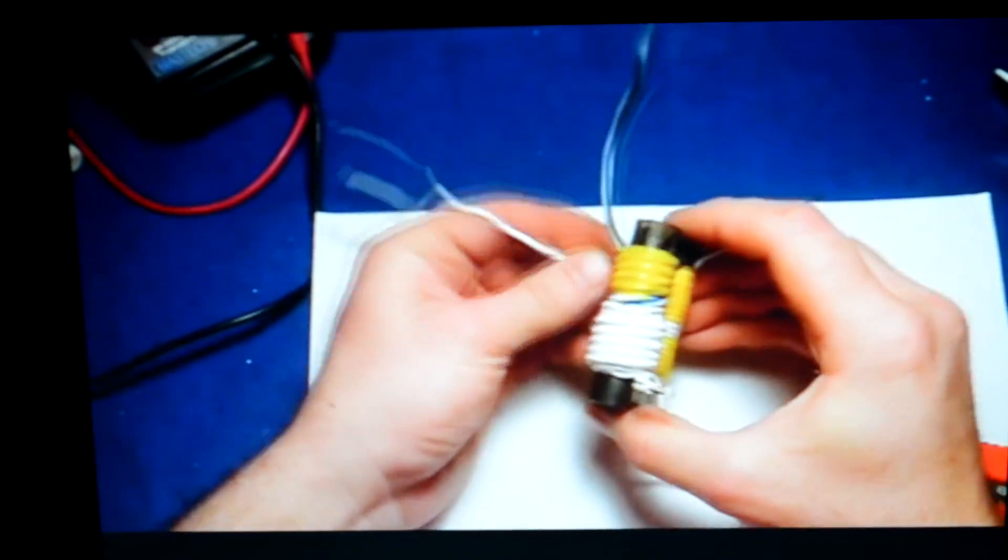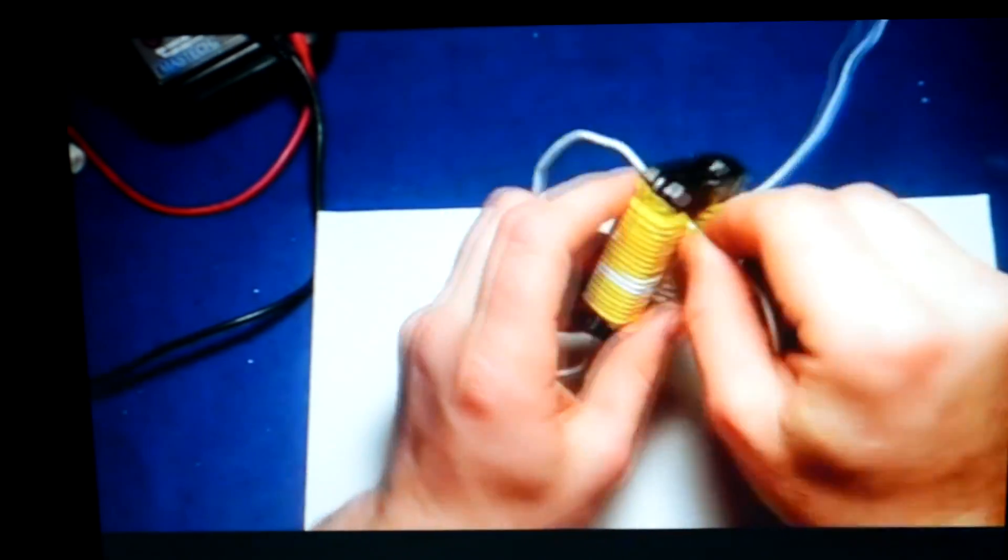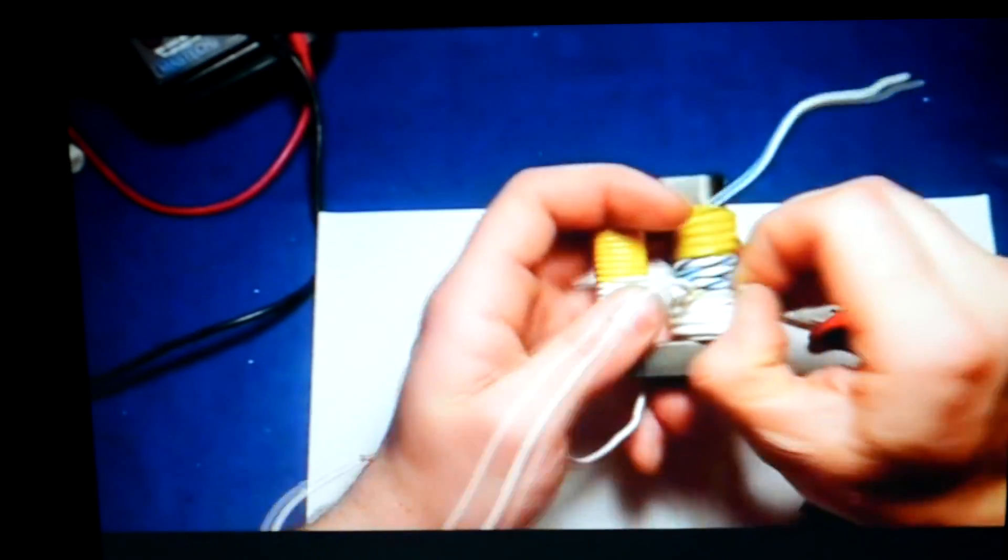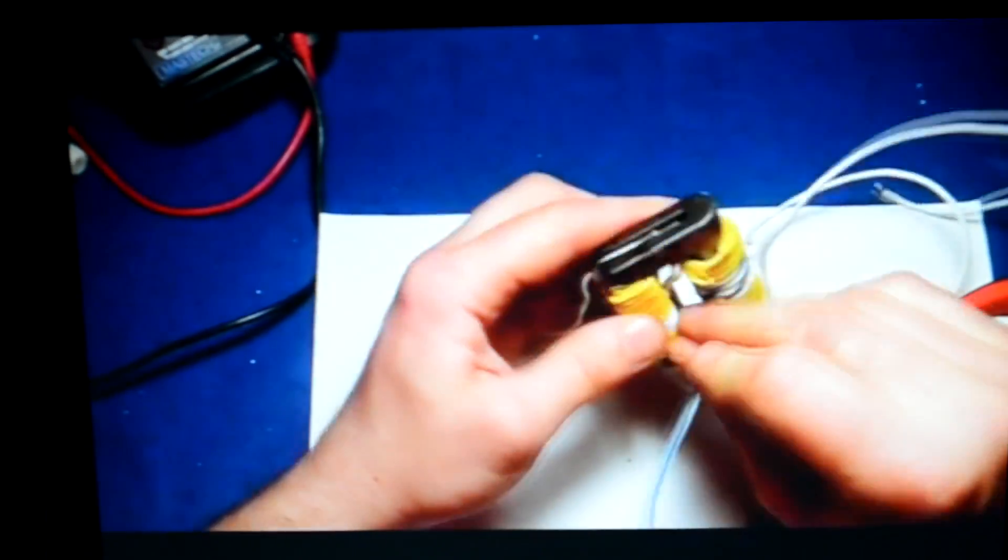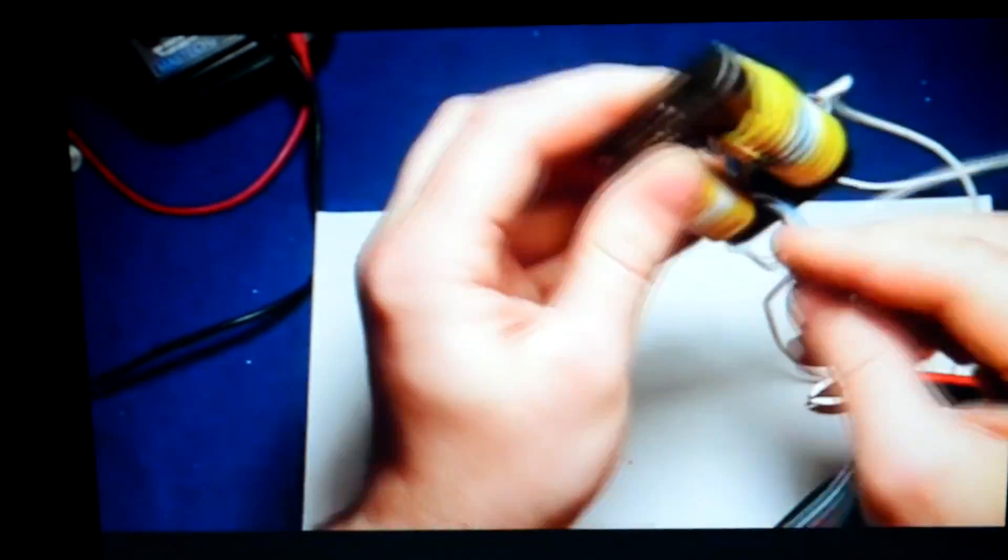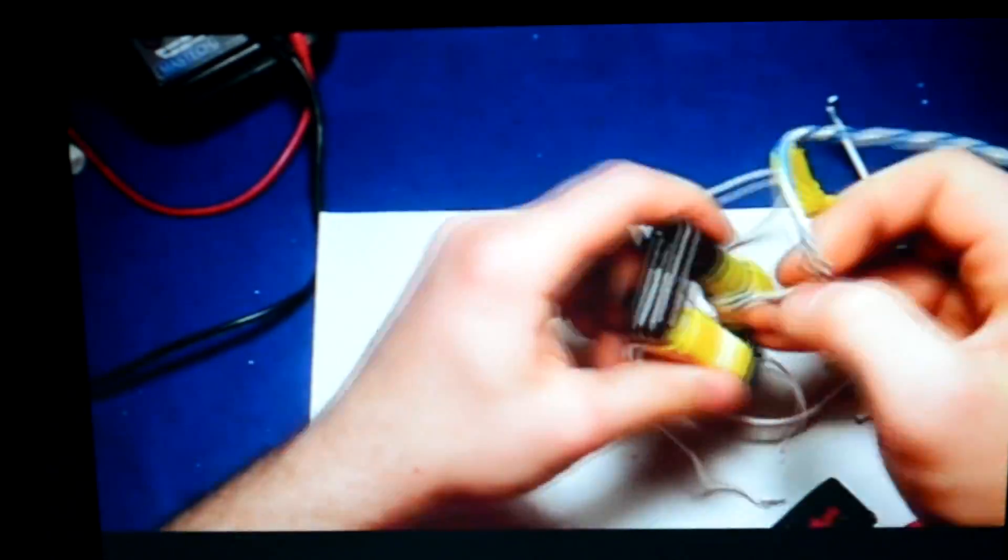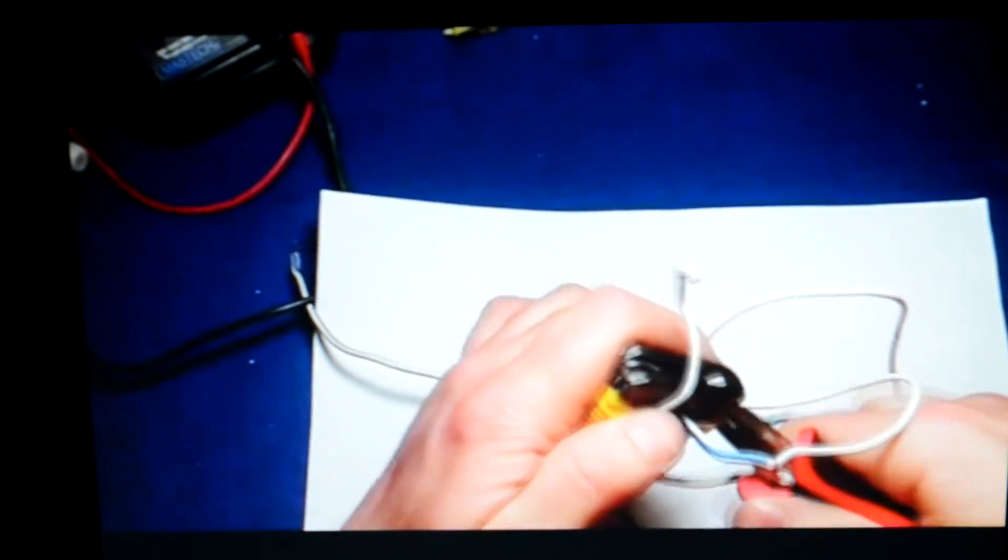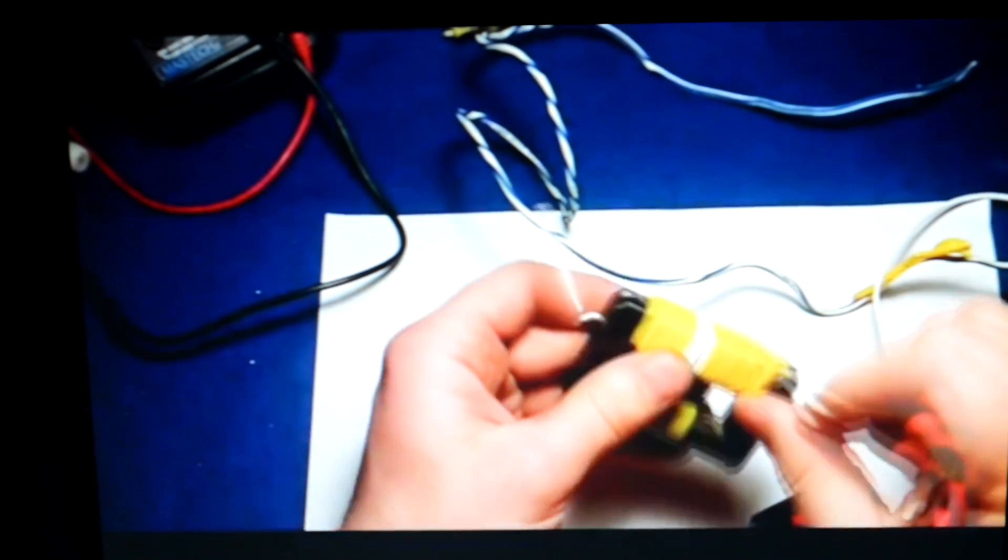Now the ferrite by itself is made of tiny, tiny, tiny powder that is mixed with a binding compound and then put on press to have a shape of the ferrite. So each one of those tiny particles behaves as an independent magnetic dipole, and the resistance of that structure is extremely high. That's why this thing doesn't keep steady magnetic flux. Once you take out the magnetic component of electromagnetic wave or whatever the electromagnetic field you have there, each of the domains will go its own way. So this thing doesn't hold magnetism.